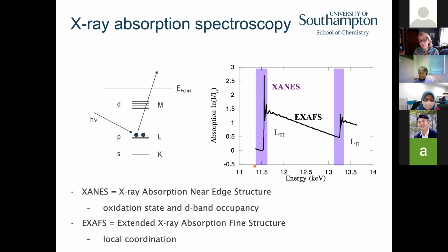Right at the energies of the transition is the XANES region, and the wiggles that we see out here are the EXAFS. So we can interpret the XANES in terms of the position of this edge and the intensity of this thing we call the white line, which is the first peak beyond the edge. So the XANES is going to give us oxidation state, and where we have changes in the white line and we're working at the L edge, we can say something about the d band occupancy of the atoms of the metal. The X-ray absorption's fine structure, these wiggles, we're going to analyze those to give us the local coordination.